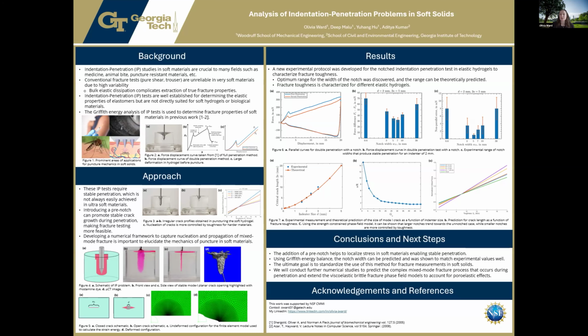Next, we use a Griffith energy balance framework to analyze the system. In simple terms, fracture occurs when the energy available from deformation is sufficient to create new crack surfaces. Using this idea, we can predict the size of the crack and relate it to measurable quantities like force and displacement. We also used a finite element model in Abaqus, shown in Figure 5. The complex geometry of the indenter tip requires us to use FEM, and we use this to calculate the strain energy in both the undeformed and deformed configurations. This allows us to quantitatively predict crack growth under different conditions.